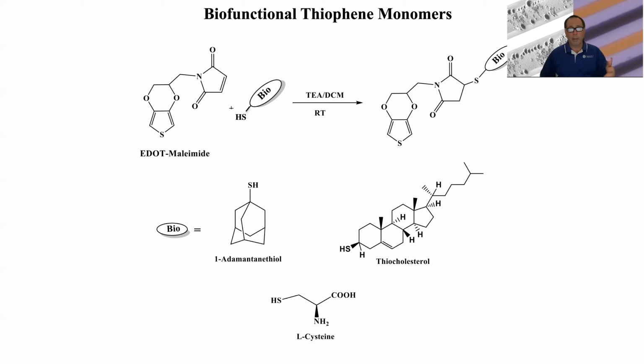And the maleimide itself can undergo a reaction similar to the thiol-ene, where you have now a thiol on a bioactive molecule, and you can click on your bioactive molecule to make a functionalized monomer, or you can make the polymer and click it onto the polymer at the end. And again, some of the groups we've looked at so far include adamantane, a relatively bulky hydrophobic group, a surface active molecule like cholesterol, and an amino acid.